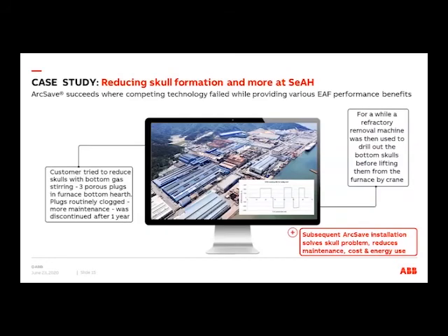Another customer which also used to have the skull formation was SeAH in South Korea. Here we installed the ArcSave on a 70-ton electric arc furnace with the EBT tapping system. They had a tap-to-tap time of 65 to 75 minutes using 90% scrap. They produced annually 180,000 tons of tool steels and stainless steel.